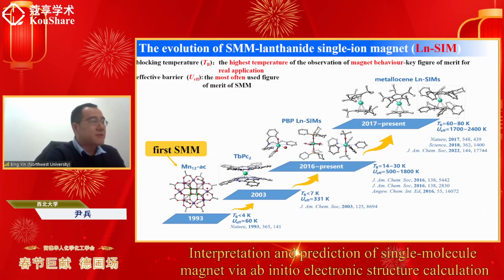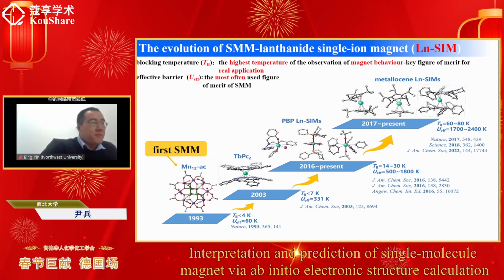After 10 years of the first report of a single molecular magnet, researchers found that to have a single molecular magnet, we do not necessarily need several ions in the system. We could have only one suitable metal ion, especially a lanthanide metal ion. And this system would also show the single molecular magnet behavior. The first report of this type of single molecular magnet is in the year 2003. Since there's only one magnetic ion in such kind of single molecular magnet, they are also termed single ion magnets. And then the single ion magnet gradually became one important frontier in the field of single molecular magnets.